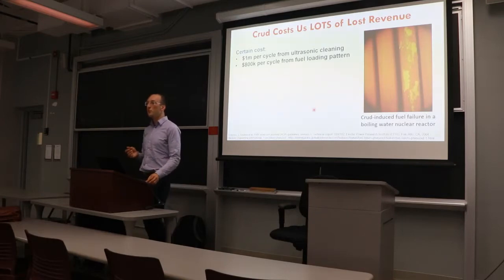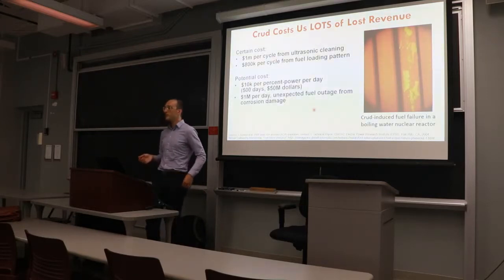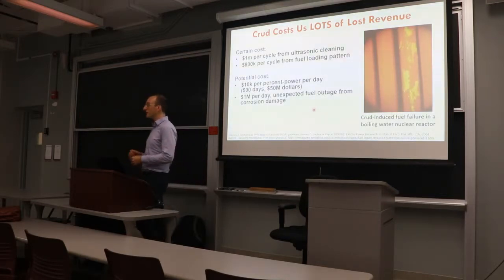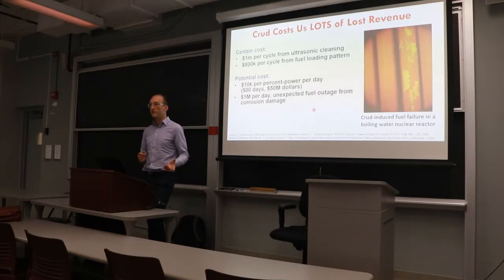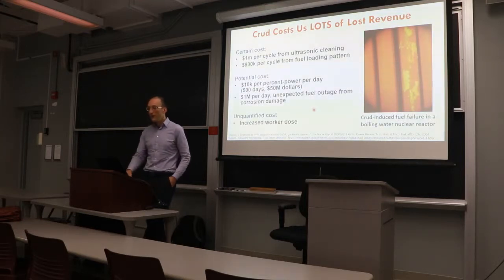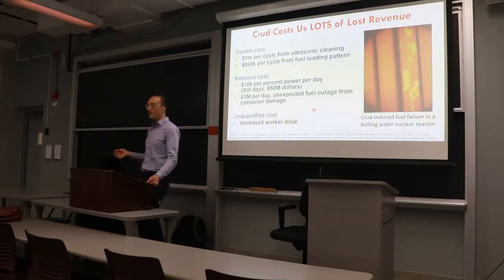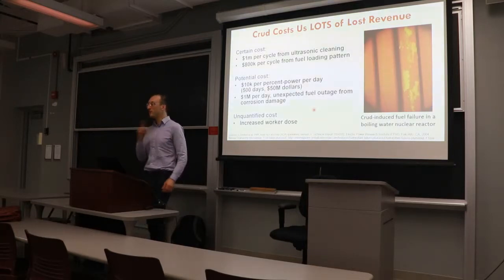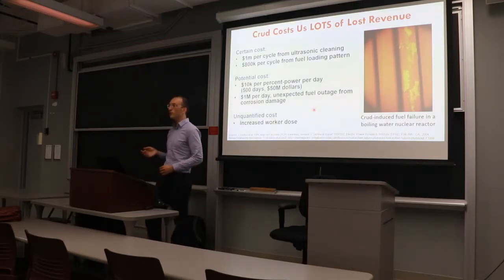And then you actually have to buy more fresh fuel to reduce the amount of boiling that's causing the crud to form. And if things go worse, you lose about 10K per percent power per day from required derating of your plant. And if crud causes any sort of severe corrosion issues like leaking fuel, you've got to shut down early, and that costs you $1 to $2 million per day in lost power. And there are worker dose concerns: this crud gets radioactive, it gets spread around the plant, and it then takes 32 or 40 welders to do the job of one, because you have to keep swapping people out when they hit their maximum radiation dose.